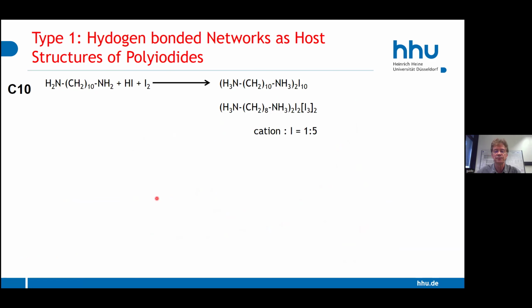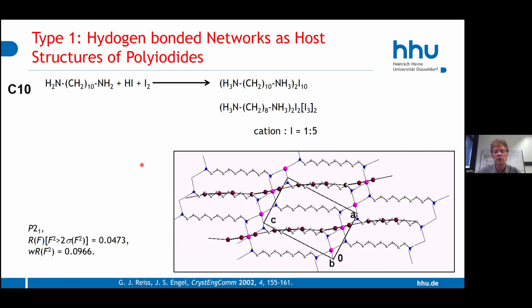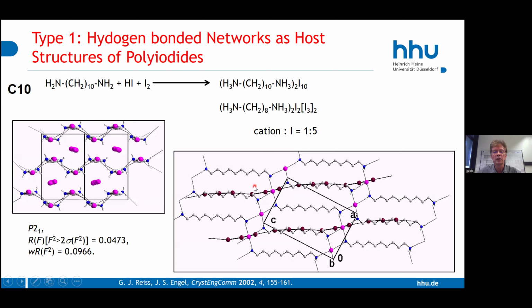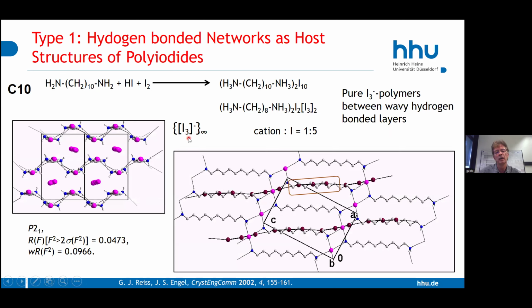We go to C10. When we go to C10, we also get an organic framework, hydrogen bonded by these iodide anions. We always see this square motif, and within this polyiodide, we only have I3 minus anions. So it's simply a simple polymer which is created by this I3 minus. Yes, and they are always located in these channels. This structure is already published, and it made a lot of problems.